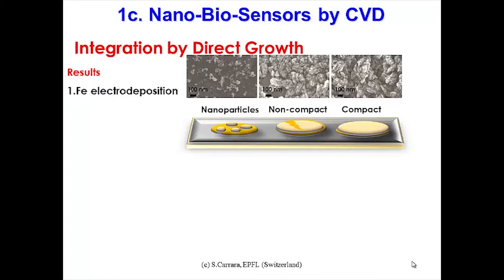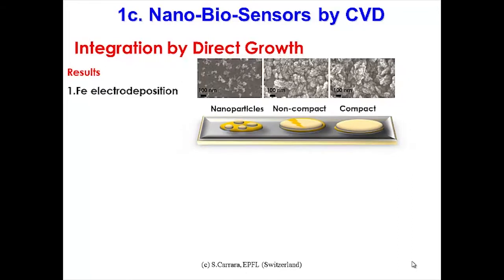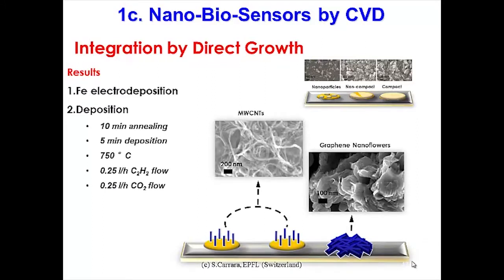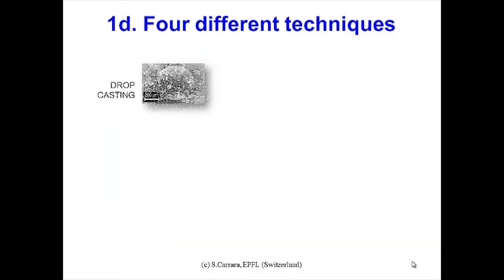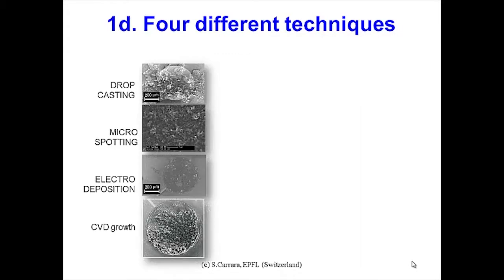As I said, we deposit the iron by electrodeposition, then we put this structure in the chamber, and we obtain a typically different kind of structure: carbon nanotubes that look really like what we have by drop casting, or flowers of graphene, graphite, and similar kinds of carbon-based materials. Very briefly, we can compare the different materials we obtain, a different kind of nanostructure at the electrode: drop casting, micro-spotting, electrodeposition, and chemical vapor deposition growth.